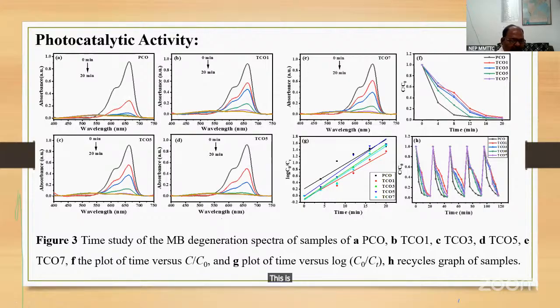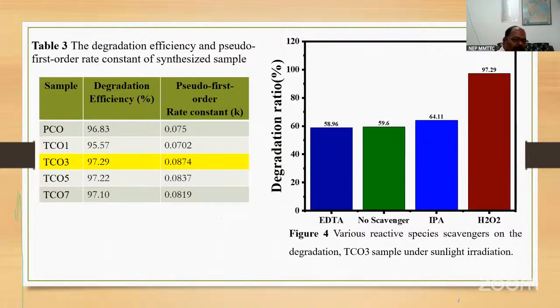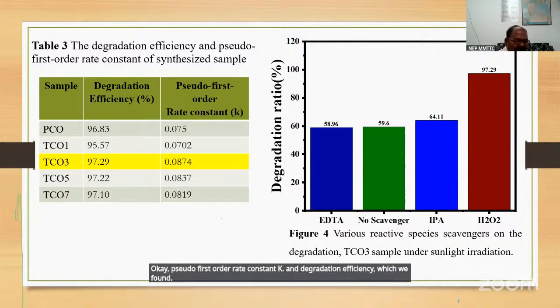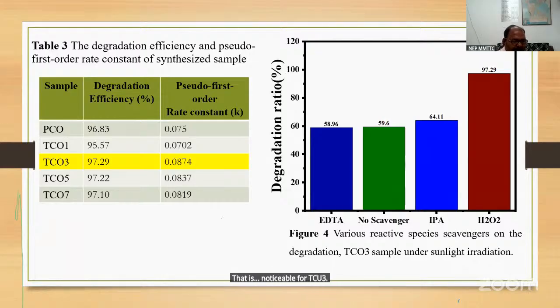This is the time study of the methylene blue degradation, the spectra of samples, and the plot of time versus log. The degradation efficiency and pseudo first order rate constant of the synthesized samples. The pseudo first order rate constant K and degradation efficiency, which we found, are noticeable for TCO3, titanium cobalt oxide, 97.29. These are the scavengers.